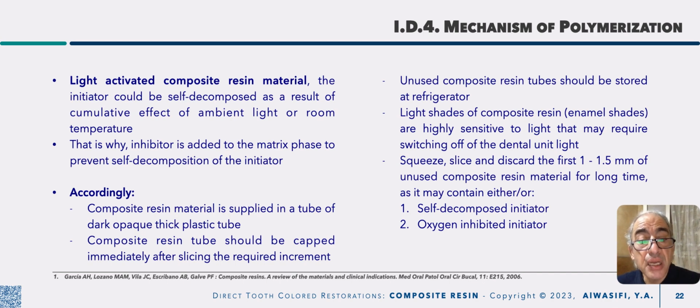For light activated composite material, as we mentioned, it could self-decompose as a result of the cumulative effect of ambient light. That's why they added an inhibitor to prevent this self-decomposition. Accordingly, your composite material is supplied in a dark opaque thick plastic tube, and the composite resin should be recapped immediately after slicing the required increment. Unused composite resin tubes should be stored in the refrigerator. Remember that light shades are more sensitive to light than darker shades, so sometimes you should switch off the dental unit light, especially when using light shades and enamel shades.